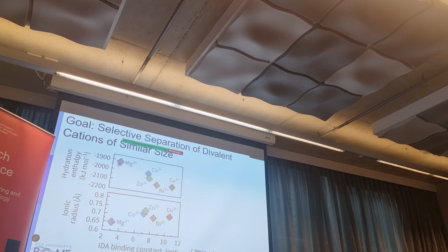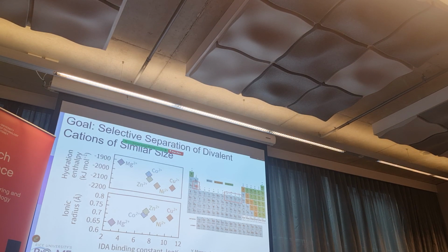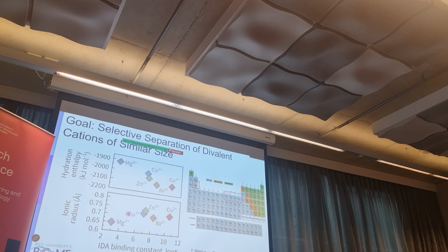Now we selected the separation of divalent cations of similar size: cobalt, zinc, nickel, and copper. As a comparison, we also included magnesium. These four metals that we're interested in are quite relevant to batteries—they're more like transition metals—and magnesium is just for comparison. As you see, looking at the scale here, they have roughly the same hydration energy and roughly the same size. This is the ionic radius, or the naked ion radius, in angstroms.